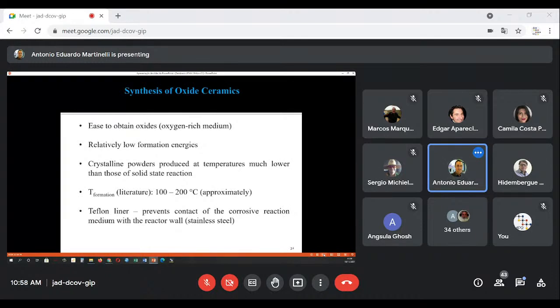Okay, we are now divided into two classes of ceramics. We start with oxide ceramics, which is the example I'm going to give today. But the method, the solvothermal synthesis, can also be used to produce non-oxide ceramics. Oxide ceramics are easy to obtain because oxygen-rich mediums are easier to control. The formation energies are relatively low, especially compared to non-oxide ceramics. The crystalline powders are produced at temperatures much lower than those of the solid state reaction, which is one of the main advantages of this method. The formation temperature of some oxide ceramics may range between 100 and 200 degrees, which is very different from those obtained from solid state reaction.